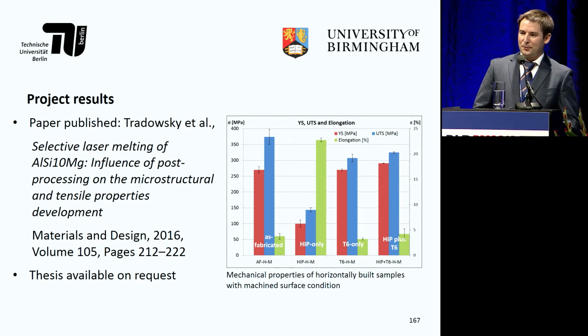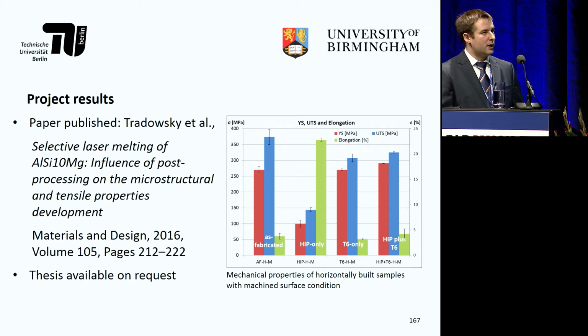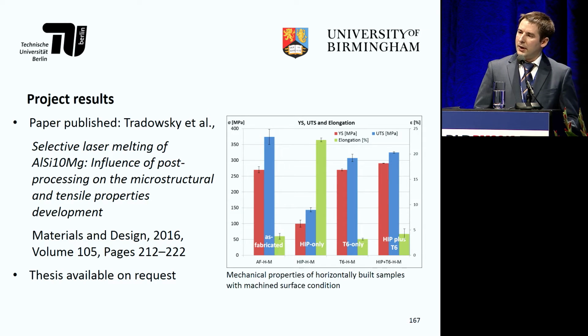I received a lot of very interesting results. Obviously, I cannot go into detail here. However, on the right side, you can see a graph. You can see that the as-fabricated selective laser melted condition was best in terms of the ultimate tensile strength, and that the HIP plus T6 treated condition was best in terms of the yield strength. If you want to see more details, there is a paper published containing the results of my thesis, and if you want to read further, the thesis is available on request.